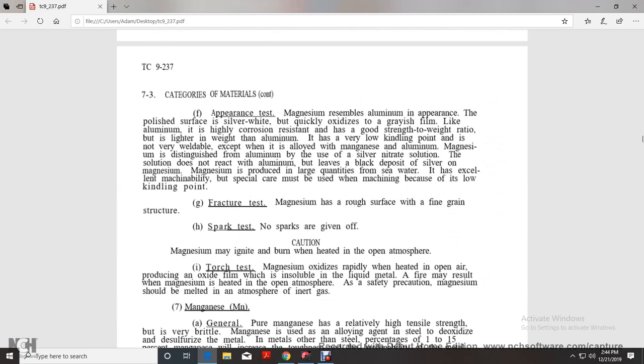All right, appearance test. Magnesium resembles aluminum in appearance, with a polished silver-white surface, but it quickly oxidizes with a grayish film like aluminum. It has high corrosion resistance and a good strength-to-weight ratio, but is lighter than aluminum, has a very low kindling point, and is not very weldable except for alloyed magnesium. Magnesium is distinguished from aluminum by use of silver nitrate solution. The solution does not react with aluminum, but leaves a dark deposit of silver on magnesium. Magnesium is produced in large quantities from seawater. It has excellent machinability, but special care must be used when machining because of the low kindling point.